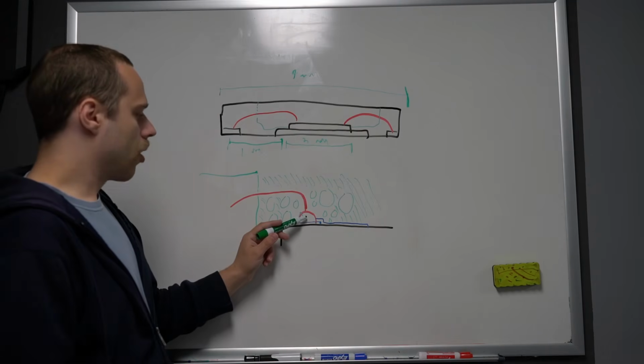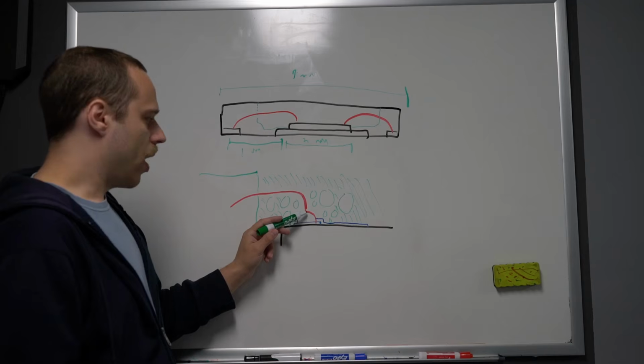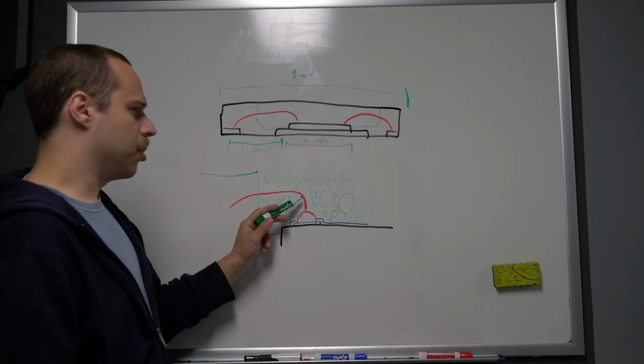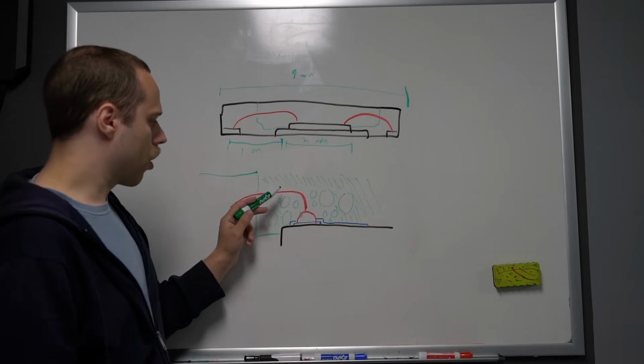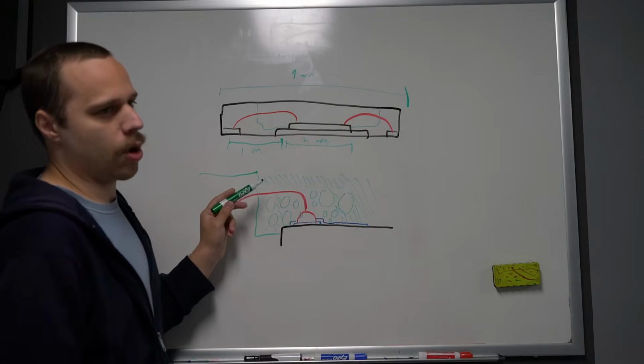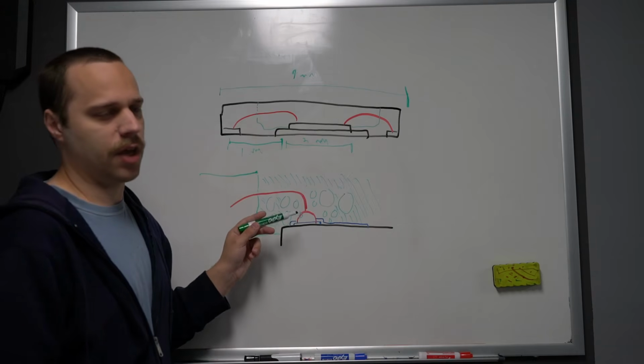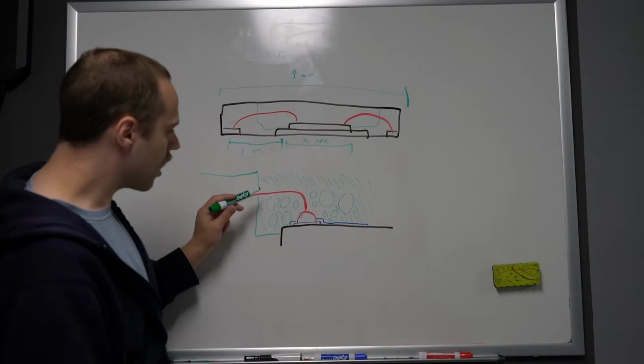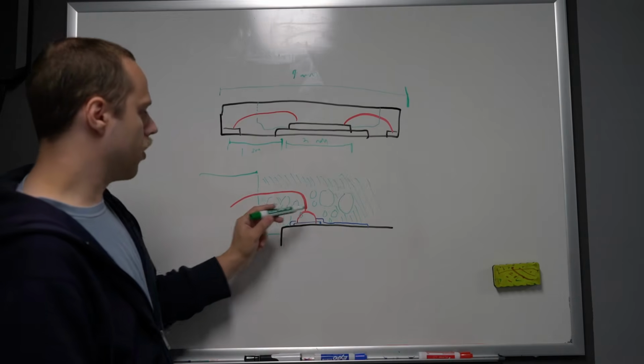So our bond wires are made of copper with a palladium coating, and I believe there's a very thin gold flash over the surface as well. We can essentially ignore that. It's not thick enough to provide any significant corrosion protection. And so we want to be able to remove all of this material.